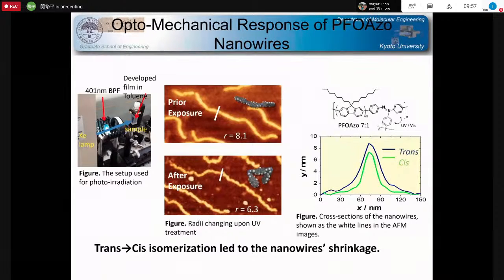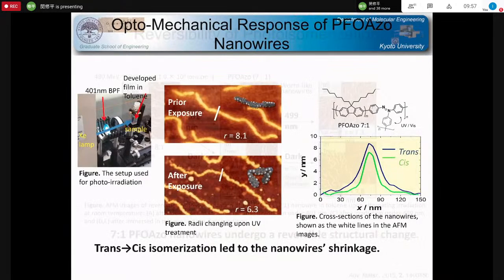And as we expected, the morphology of the nanowires changed from the straightforward stretched form to a wavy zigzag form, as shown in the bottom AFM images. Here you see we had also succeeded in realizing photoresponsive one-dimensional nanowires by using light irradiation.